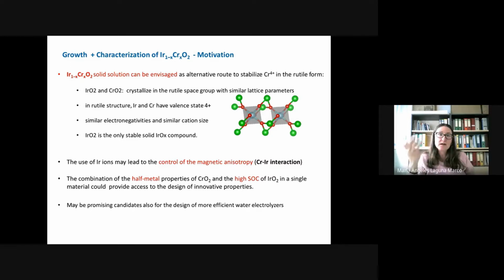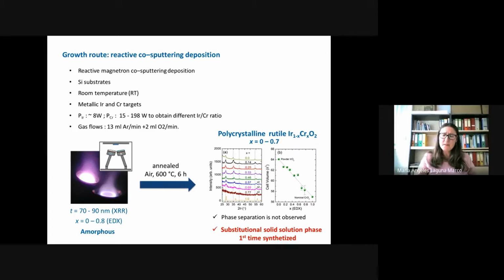In addition, iridium has been chosen as the dopant element because it may lead to the control of the magnetic anisotropy. Compared to the localized magnetic moment of rare earths, the more extended 5d orbitals of iridium may prove to be more efficient in inducing hardness. In addition, these oxides would combine in a single material the half metal character of the chromium oxide and the high spin orbit coupling of iridium dioxide. This could give rise to innovative properties and devices.